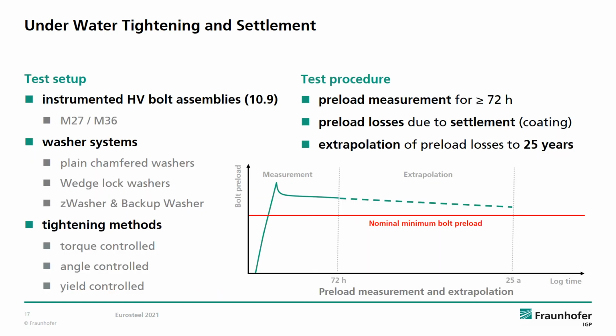We used regular plain chamfered washers as well as the other washer systems mentioned earlier and the tightening methods listed below. After tightening, we measured bolt preload for about 72 hours. Doing so, we could see the initial bolt preload applied with the different tightening methods, and we could also detect the according preload losses. For a conservative view on bolt preload over the lifetime of the bolted connections, we extrapolated preload losses to a theoretical lifetime of offshore wind turbines of 25 years.